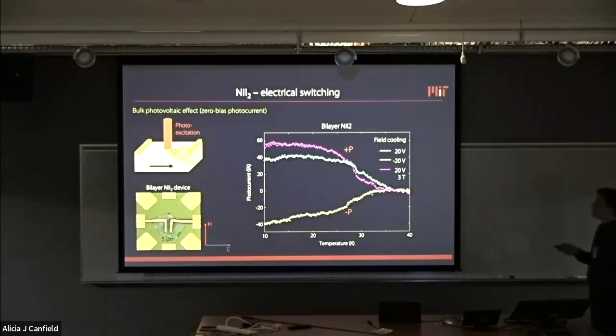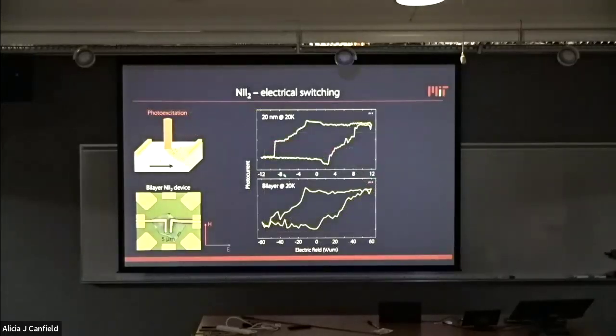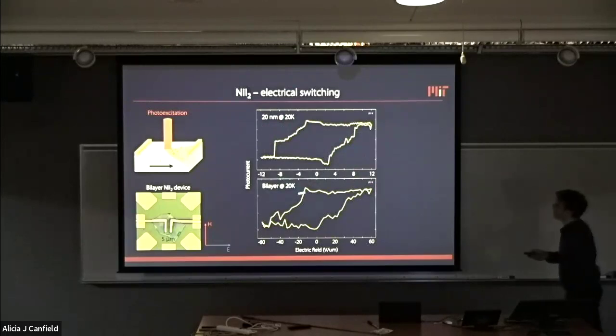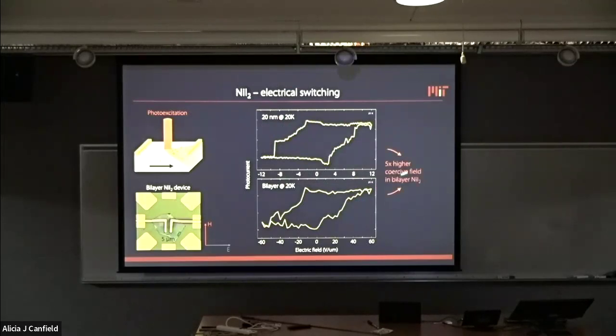So we can measure this all the way down to the very, very ultra thin. So we see these two polarization states, positive and negative, with a little bit of a magnetic field dependence, although that hasn't been explored in detail. And there is interestingly a significant difference in the coercive fields for 20 nanometer thick samples versus two-layer thick, which is about 1.2 nanometers. So the coercive field increases by about a factor of 5, going from the bulk-like samples all the way to the ultra thin sample. And we don't yet understand why this is happening. This is still an open question for us.